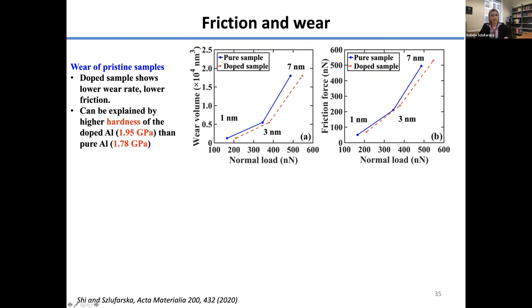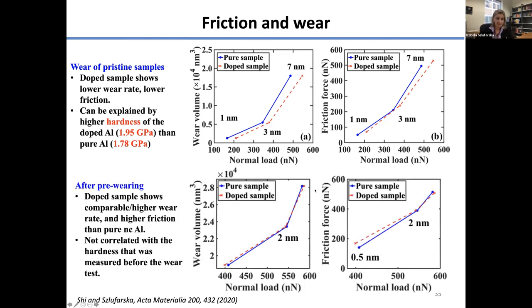Now, we then performed another test, which I think is more interesting, where we first scratched the sample multiple times, because again, remember, we were interested here in the evolution, not just a single measurement. So we scratched the sample multiple times over the same location, as you may expect in applications. So it was the pre-wearing. And after some pre-wearing, we performed again a test measuring friction and wear volume as a function of normal load. And what we found is that in this case, the trend was reversed. The pure sample had a better wear resistance. The pure sample is the blue one. So it's lower, comparable to the doped sample, and has a lower friction force. So the trend was reversed.